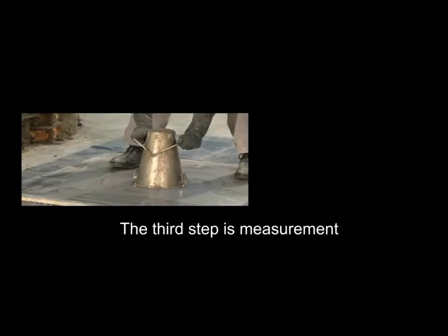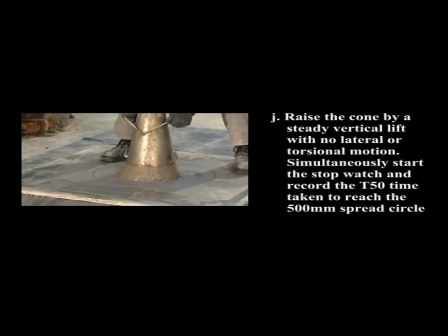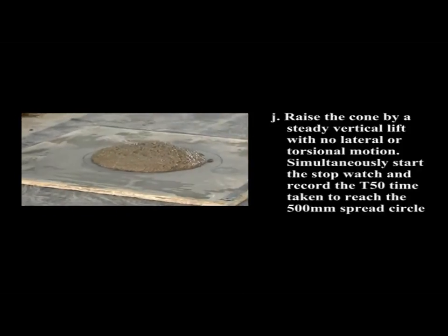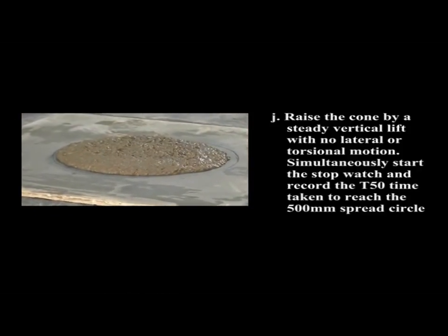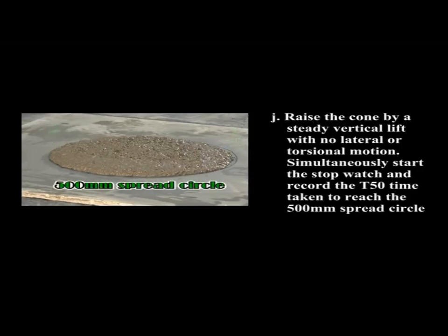The third step is measurement. J. Raise the cone by a steady vertical lift with no lateral or torsional motion. Simultaneously, start the stopwatch and record the T50 time taken to reach the 500 mm spread circle.